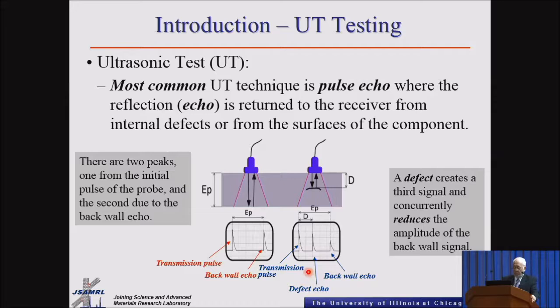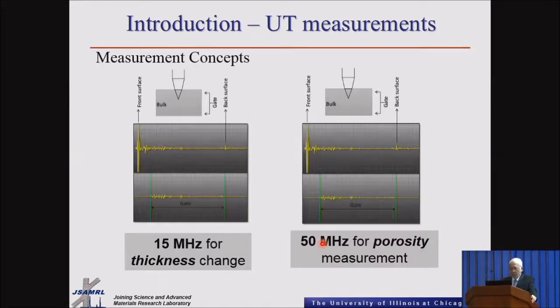So basically, in the case of the pulse echo, as we know, you use a probe that is both a transmitter and a receiver. In the case that you don't have any defect in your material, you get 2 particular peaks. Now, if you have a defect, then you have more peaks that are going to come into this screen. So that is one of the ways that you are going to detect some of the defects.